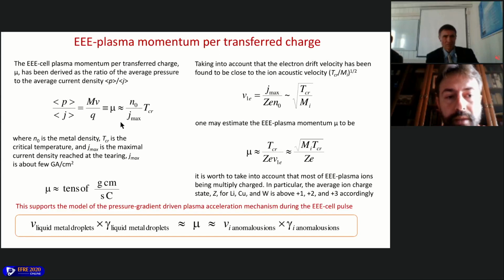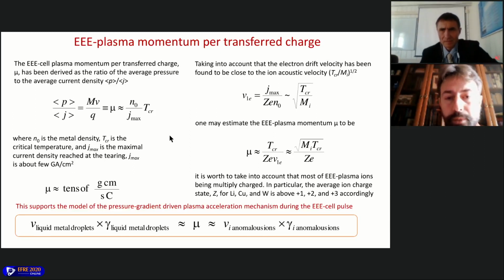And this is characterized by the ratio of average pressure of the pulse to the average current density. So we have strong variation in pressure and in current density, and we can estimate the average values over this pulse. This value can be estimated to be about tenths of gram centimeter per second coulomb, and this value is close to the product of the velocity of ions that can be measured and the specific erosion of ions, and also it corresponds to the velocity of droplets that can also be measured, and the maximal erosion rate for liquid metal droplets can also be measured. So this momentum per transferred charge is responsible for the erosion processes.